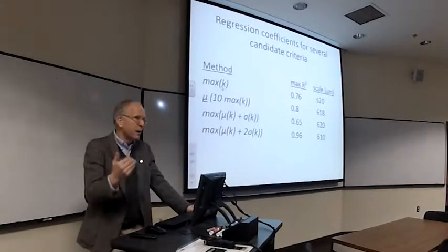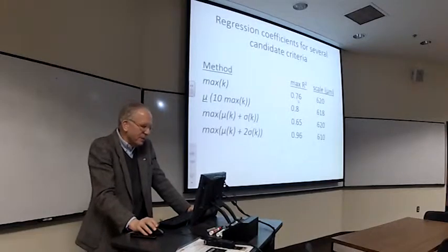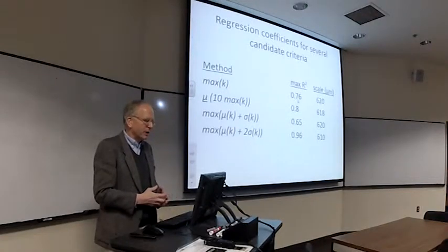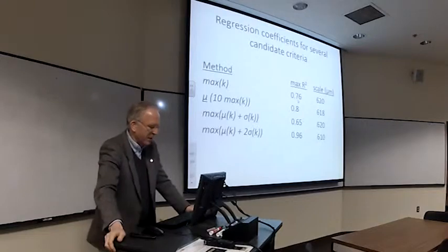Now, on each of these measurements, she looked at 1,120 profiles from each measurement. So, all right, we'll just take the maximum. And so I said, all right, R squared 0.76. That means 3/4 of the variation in fatigue strength, or fatigue limit, you can explain with that parameter. So that's pretty good. I think nobody's done much better than that.